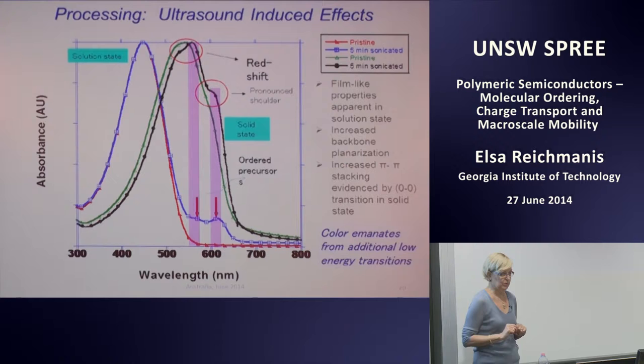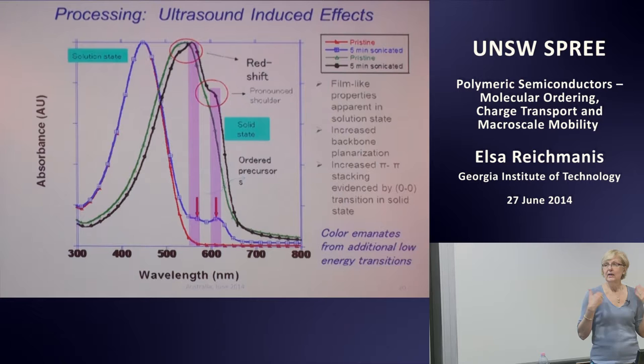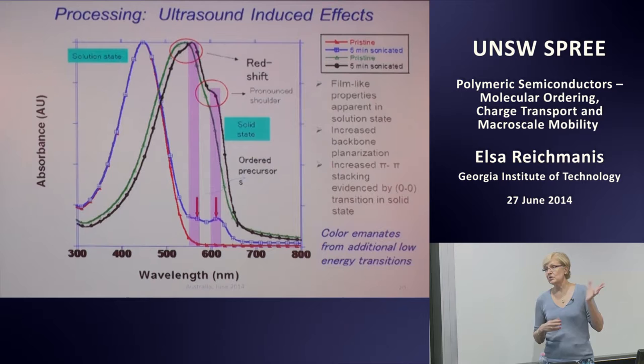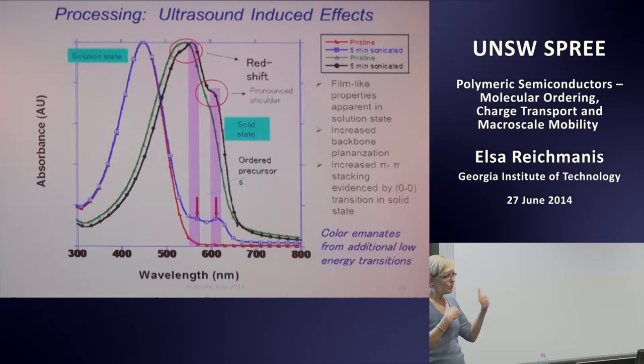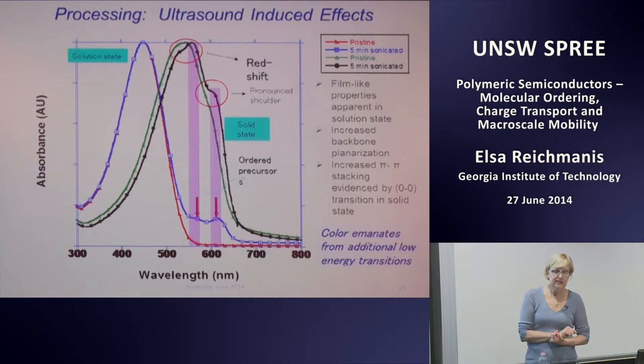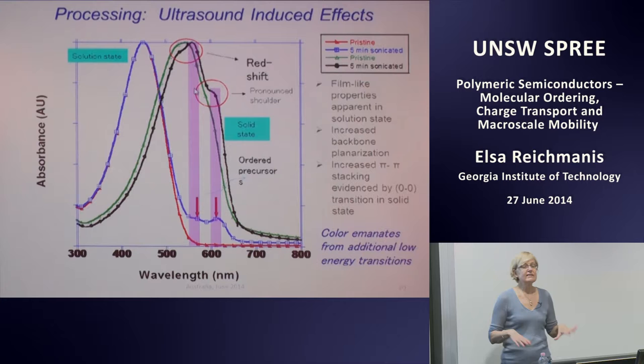All right, so if we take a solution of P3HT in chloroform and ultrasonicate it, we go from what starts out as an orange solution to one which is a dark purple, almost black solution. And in the solution state, we see the appearance of bands at lower wavelength, indicating the presence of more highly ordered structures within this solution. If we then take that solution and use it to deposit a thin film, we end up with a film that has bands that are redshifted from the untreated material, and we see a pronounced shoulder that's indicative of more pi-pi stacking, and again, a more ordered film.